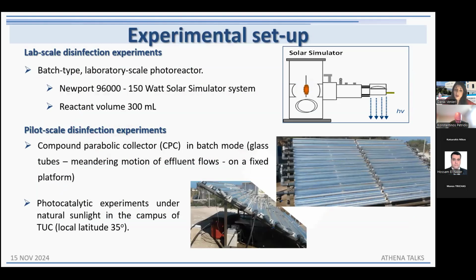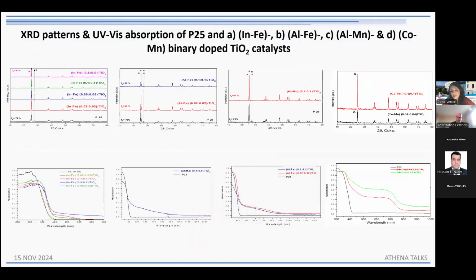And this is the collector. You can see photos of the collector in our campus. Of course, I should say that we need sunlight, possibly good sunlight, and high temperature. I mean, all those experiments were performed in temperatures from, I don't know, 27 to 30 degrees. And of course, here you can see, we should never forget the characterization of the catalyst. The binary doped catalysts in this case, different catalysts with iron, indium, aluminum, manganese, and so on. And of course, the UV-Vis spectra.